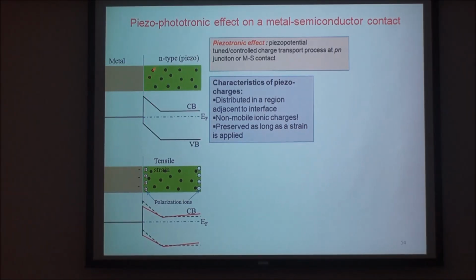And now, if you apply a strain to this, the strain produces a polar charge due to the piezoelectric effect right at the interface here. And if the doping in a semiconductor is moderate... If you over-dope it, there's no piezoelectric effect. If you under-dope it, the semiconductor property will be limited. So you have to be moderate. We found 10 to the 17th per cubic centimeter is the moderate doping for that. Okay, let me show you.